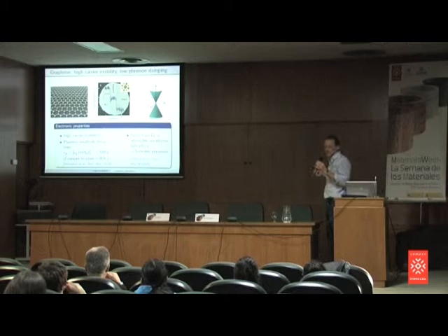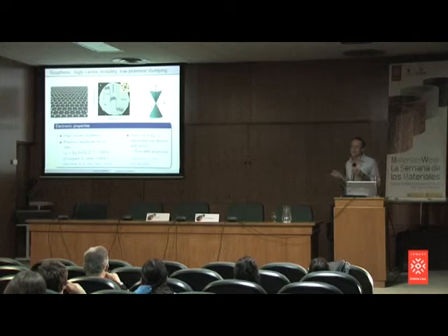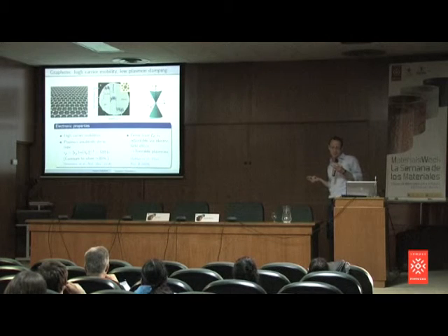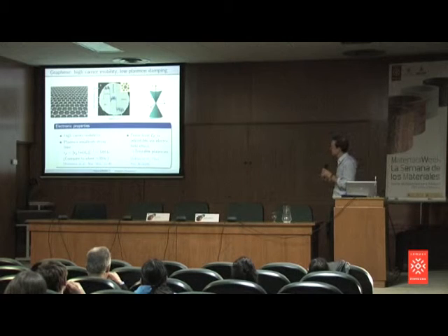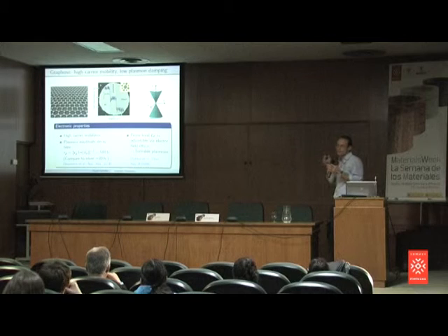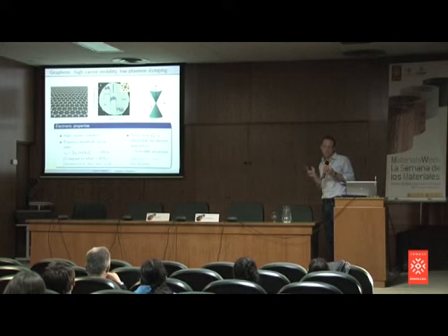And what are the practical consequences of this? We have high carrier mobilities. What is happening is that graphene is a metal, okay, but it's a pretty lousy one, actually, in terms of electron densities. There are only very few electrons in there. But what counts is the mobility, which is the conductivity per charge carrier, which is more or less the conductivity caused by one electron. This is a high number. This is comparable to good metals. If you get a good graphene sample, people can do this.